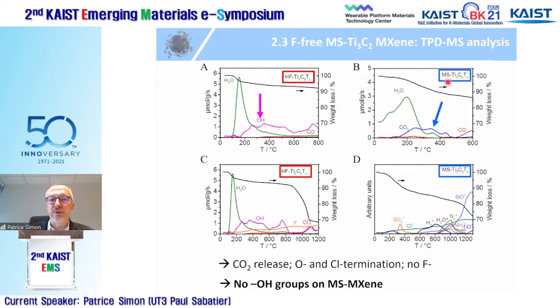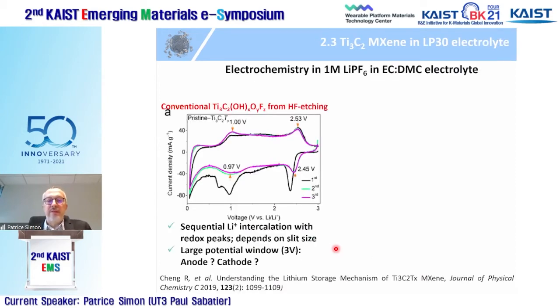In our MXene from molten salt, you still see water departure here. The intensity of the two different peaks is a bit different, but there is no OH peak. However, we see a slight gassing of CO2, so it seems that we oxidize a bit the carbon. And the conclusion of this slide is that our molten salt MXene does not contain OH groups, only oxygen, and only chlorine terminated. So there is no fluorine, no OH. And then we did some